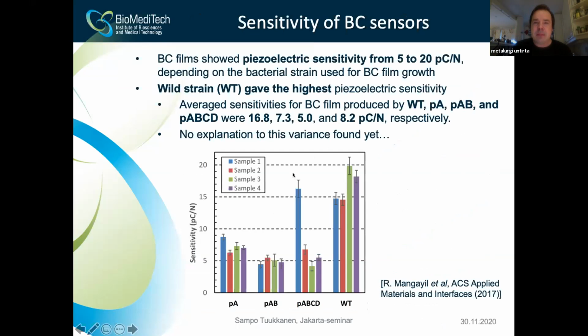Then about these bacterial cellulose films, here is a summary plot of the piezoelectric sensitivity of the bacterial cellulose films, and this varied between the films produced from different strains. And here we observe that the wild type, so this natural bacterial cellulose strain, gave the highest piezoelectric sensitivity values, which are very high. This is almost close to the commercial PVDF values, not so far from those.